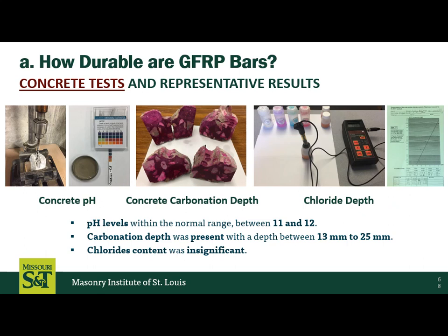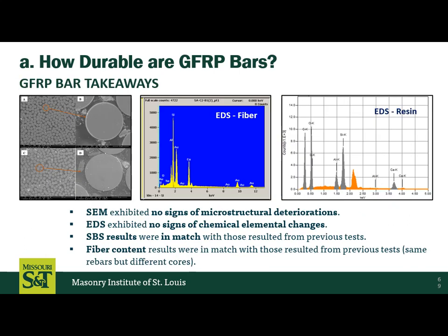Takeaway from the concrete, the pH levels in the concrete were where they'd be expected for the age of the structures. There wasn't a heck of a lot of carbonation, and the chlorides were pretty insignificant. So from the concrete side, it was doing great. From the FRP side, also doing pretty good. No signs of microstructure deterioration.